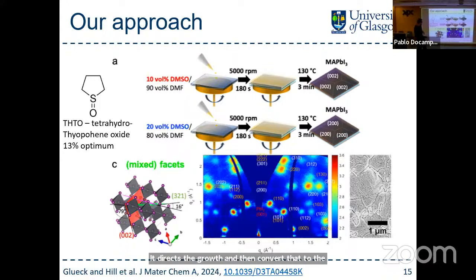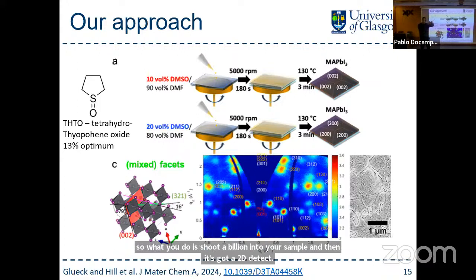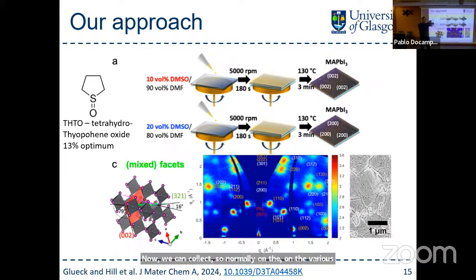Now, what I'm going to show you here is a GIWAXS measurement. Is this something that you're familiar with? Not really? Okay, so GIWAXS is grazing incidence wide-angle X-ray scattering. What you do is you shoot a beam into your sample, and then you've got a 2D detector. Normally, on a point detector, you only collect data from whatever is in that perpendicular path. With a 2D array, you collect from all the crystals in the sample. What this is good for is it gives you all the possible orientations.